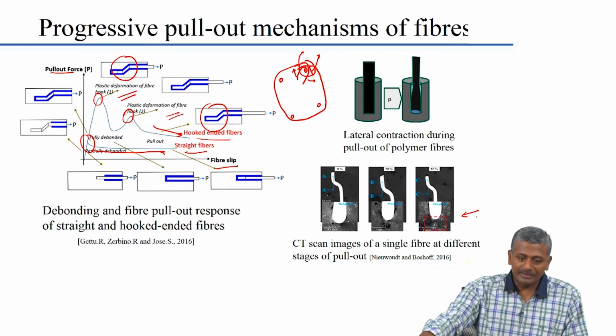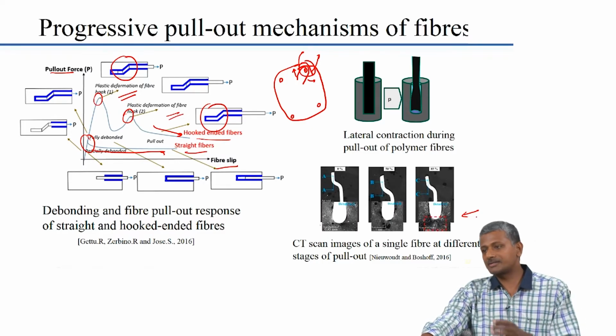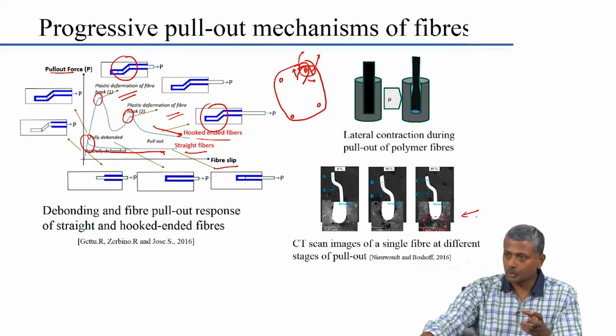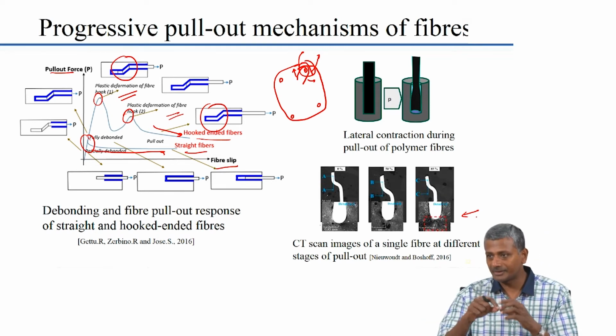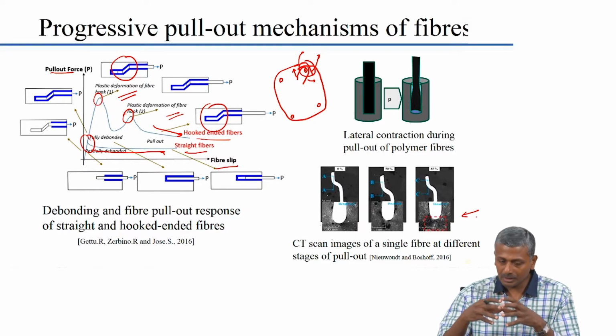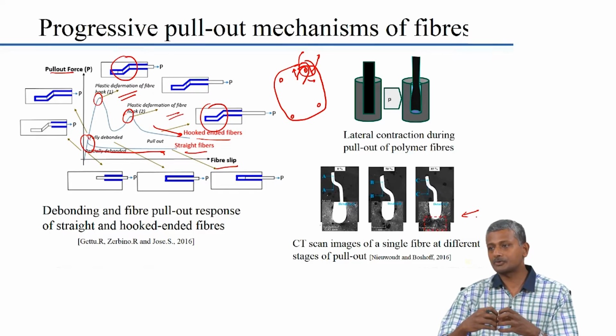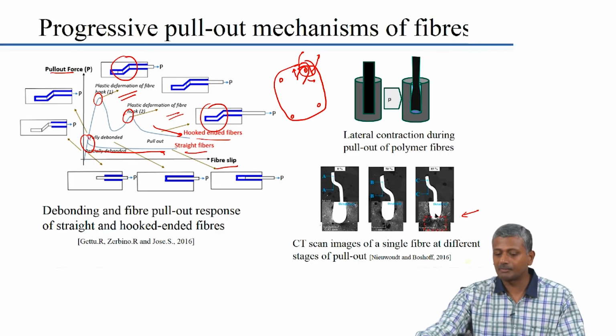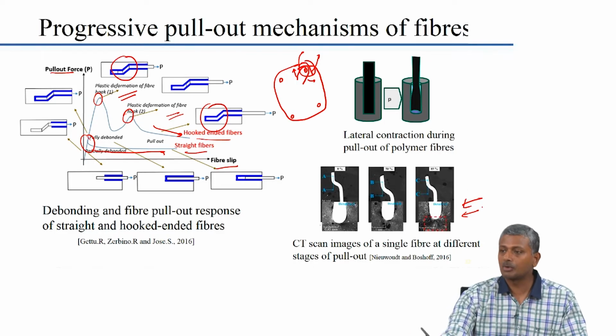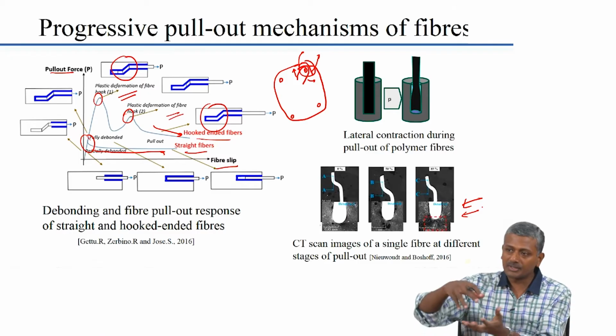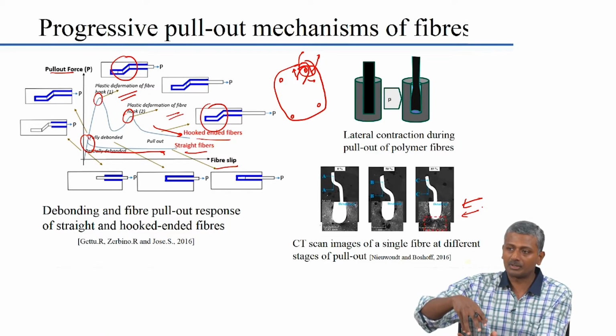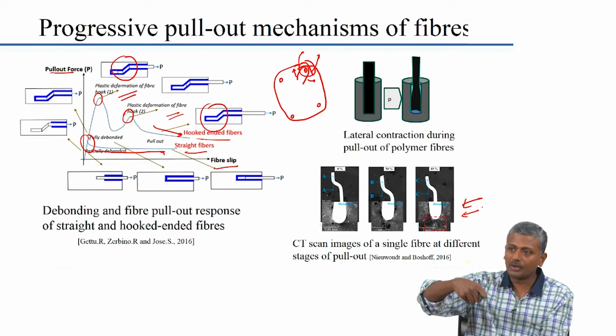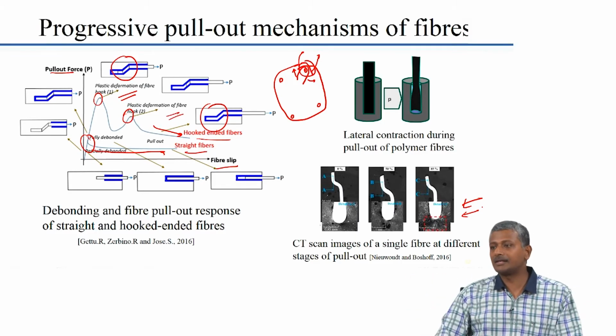Well, you can conduct this under specific circumstances. For example, there are microscopes in which you can actually do a test setup with a single fiber. So, people have actually done microscopic studies where the specimen which has a single fiber inside the system is observed under a microscope. So, you can actually set it up like that. Or you can do a tomographic study. For example, what is shown here is a X-ray tomography study where the entire setup is mounted inside the chamber of the X-ray tomography instrument, and as the pull out is going on, the X-rays are continuously scanning to get an image of the object.